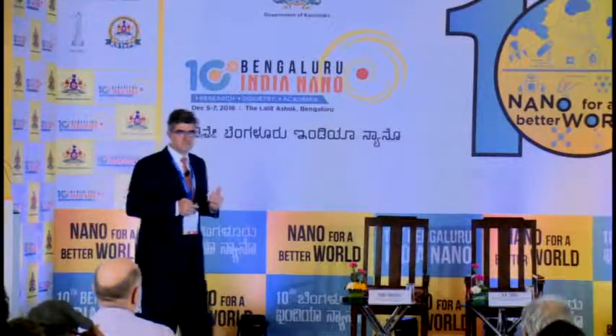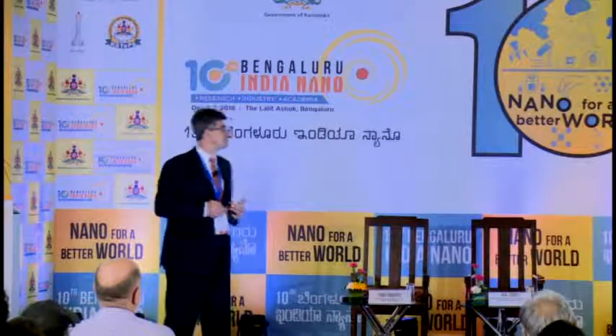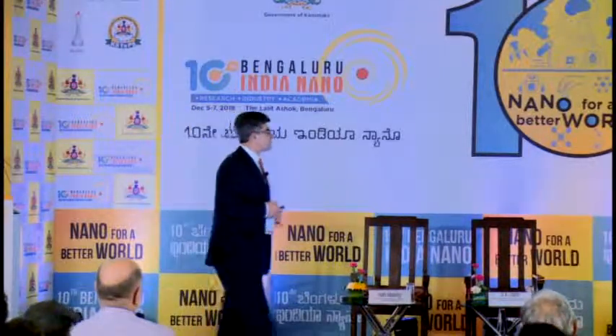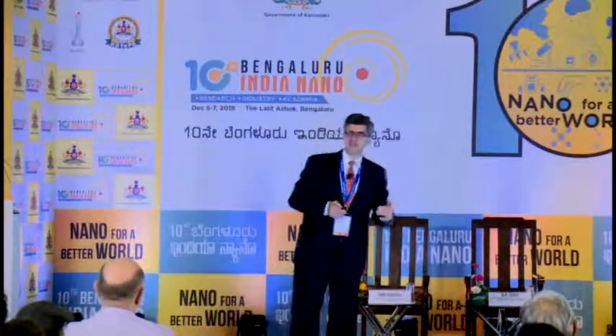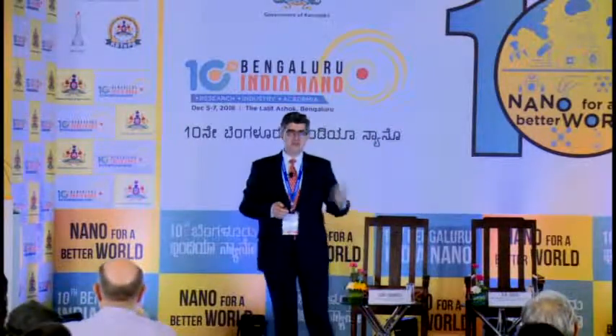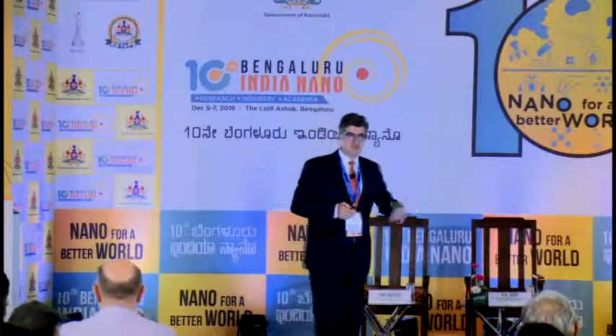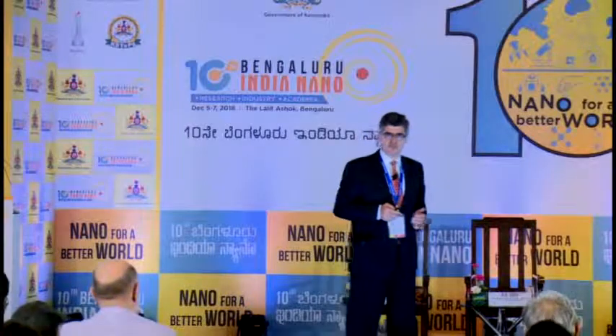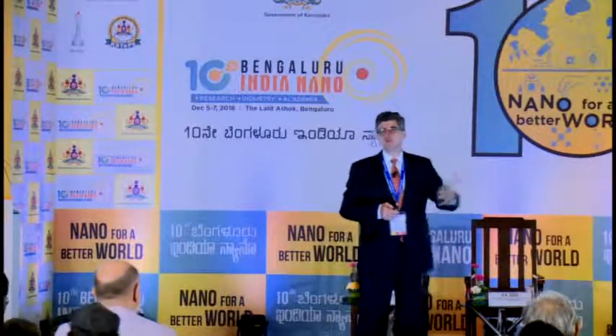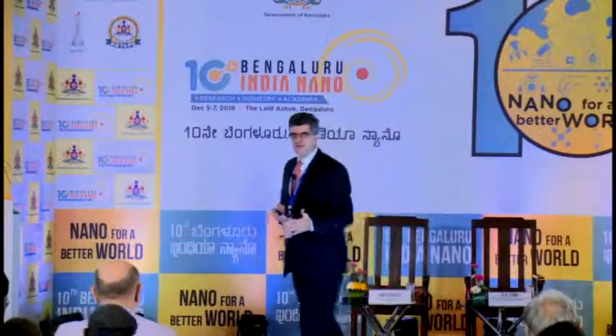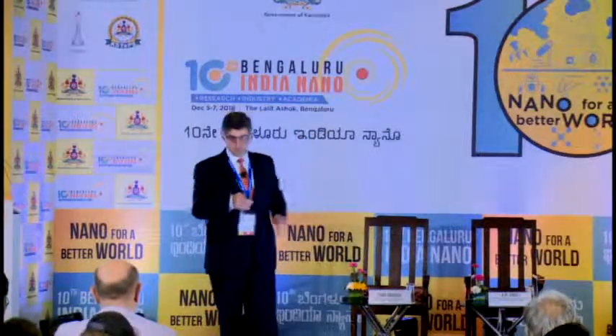But moreover, what is important? The synthesis is fairly simple. We start with ceramics known as MAX phases. My colleague at Drexel University, Professor Michel Barsoum, is known as the father of this field. He started to explore it more than 20 years ago. Those are materials like titanium aluminum carbide, titanium silicon carbide, other layered carbides here.